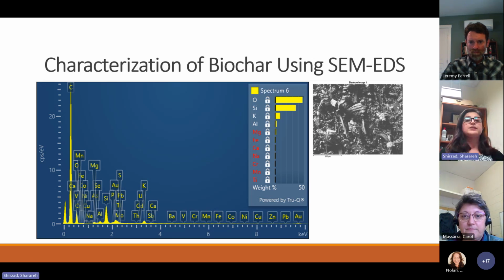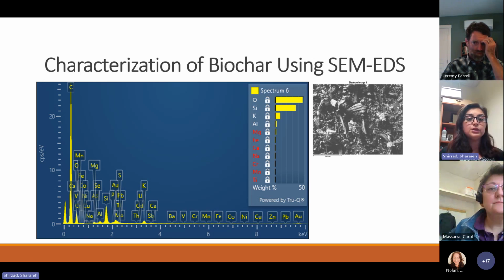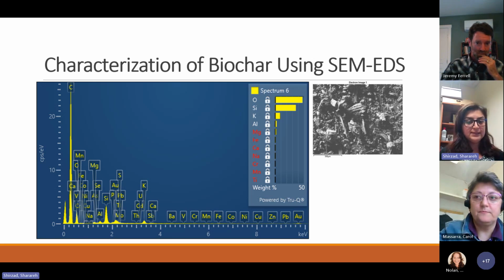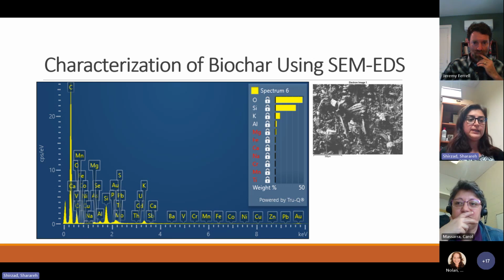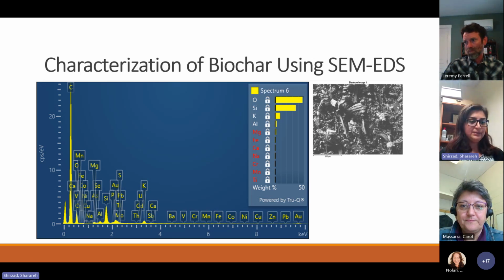So after doing characterization of biochar, we designed a concrete mixture using locally sourced sand and gravel, Portland cement, and the biochar that we obtained from the Nexus facility. We designed the mixture and we mixed our samples. We are doing wet conditioning, moist curing, and then breaking our samples after 7 days of curing, 28 days of curing, 60 days, and then 90 days of curing to see how the replacement of cement with biochar affects, most importantly, the compressive strength of concrete.